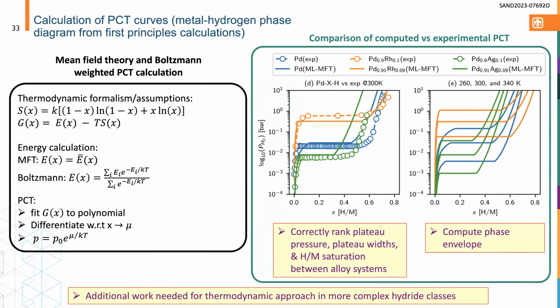So this system actually goes against the general trend of lower capacity for less stable materials. And then of course you can do this prediction at different temperatures to elucidate the phase envelope and predict the reversible capacities on the right there, or essentially the plateau widths. So we've been trying to apply this to more complicated hydrogen storage materials. There's still a lot of work to do, mainly because this thermodynamic formalism has to get a lot more complicated when the interstitial geometries get more complicated than they exist in the palladium FCC alloy.